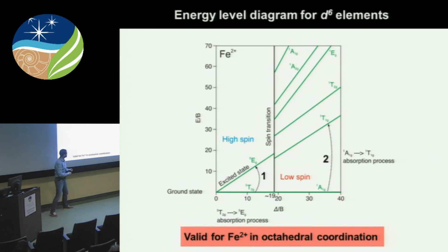We can now plot these multiplicity allowed transitions on energy level diagrams, and this is just one example for d6 elements, and Fe2+ is one example that obeys this diagram. So what you see here is basically 2 energy axes, and you can think of the horizontal axis as pressure. You can see that this diagram is divided into 2 parts. The high spin part has only one oblique green line, and oblique green lines are multiplicity allowed excited states. The horizontal green lines are the ground states. And you can see that in the low spin d6 configuration, you may have several excited states, while you have only one in the high spin state.